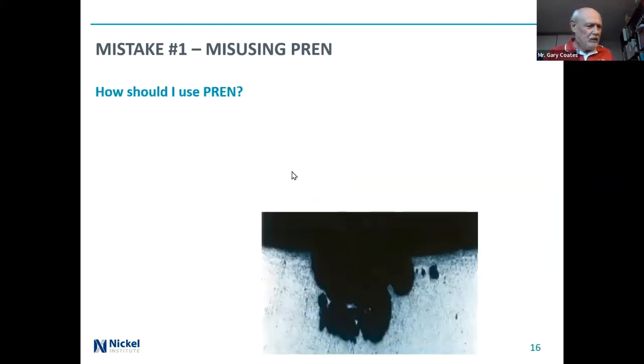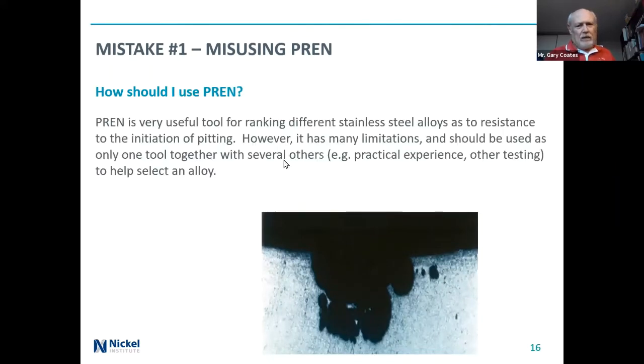How should I use PREN? So we've seen a lot of ways it shouldn't be used. Well, as we say, it is used for ranking different stainless steels to initiation of pitting. We've seen the limitations, and really it should only be used as one tool together with several others, and that includes practical experience and other testing to help select an alloy. So we know that the 6 moly stainless steels have a significantly higher PREN than 317L or 904L, and of course 316L. So that helps us to center on, if we've got a very severe environment where 316L has pitted very badly, we can say, okay, well, the 6% moly should be fine, but let's investigate it further to make sure that it will be fine.